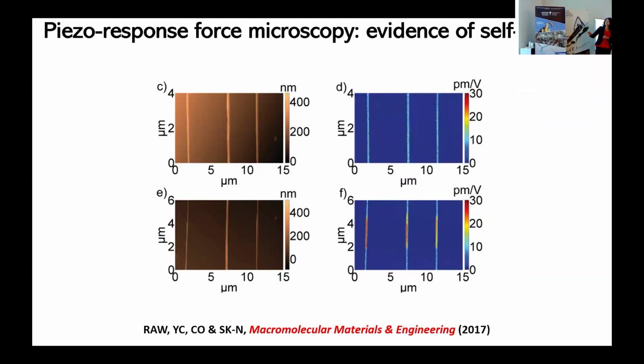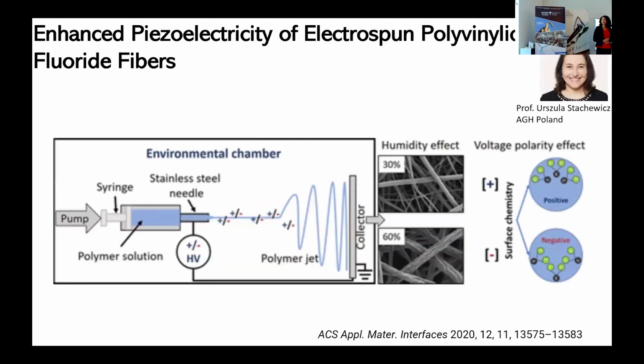So just a quick example of what these look like. On the left, you see topography images of these PVDF nanowires. And if you look at the right, these are PFM images. So this is showing you the piezoelectric response. And you can see that even just as they are, there is already a sizable piezoelectric effect. You can enhance that by using the tip to induce some poling. You can apply a DC bias, which we did around the middle, to show that you can induce the polarization even further, but just to show that even without this, the material is already inherently self-poled.